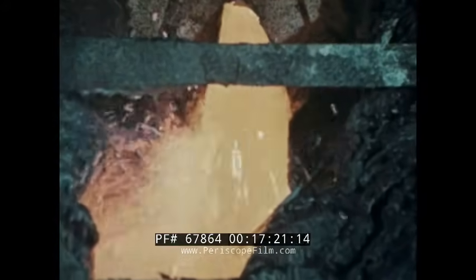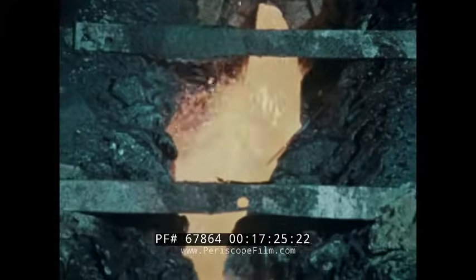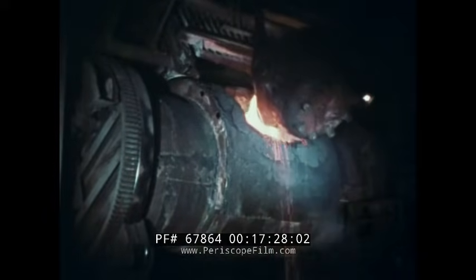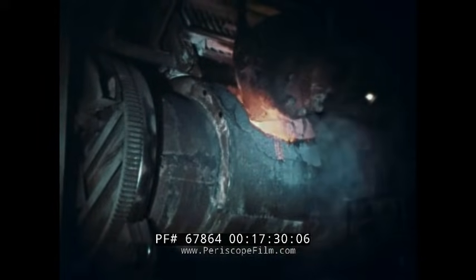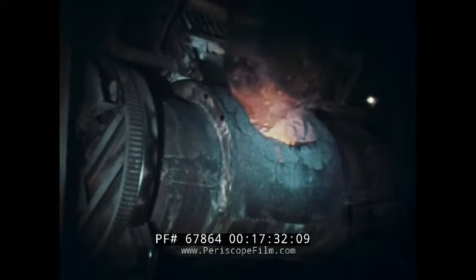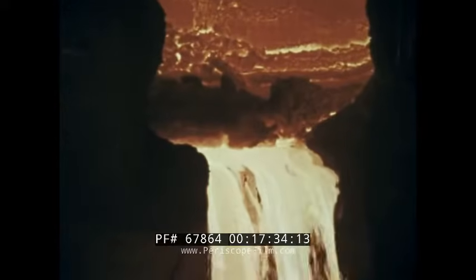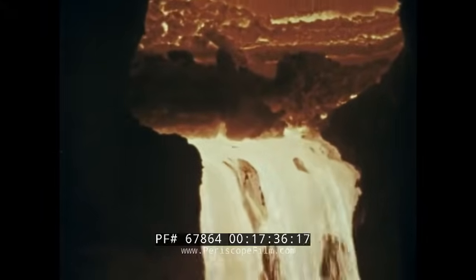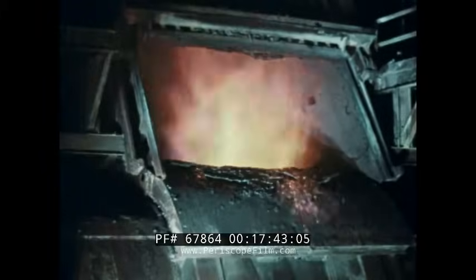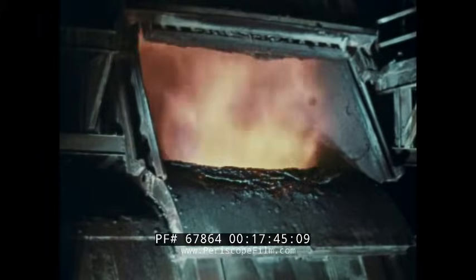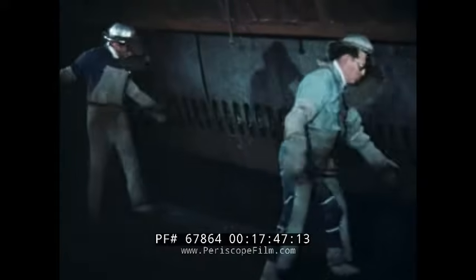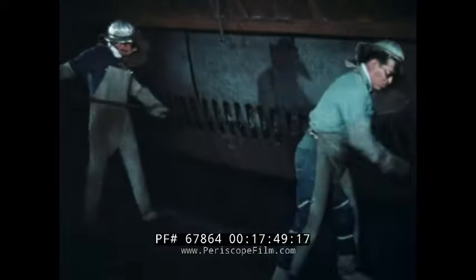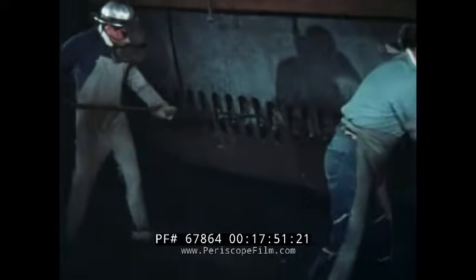The copper-bearing mat, which has settled to the bottom of the reverberatory furnace, is withdrawn and transferred to converters. In the converter, the remaining iron reacts with silica rock to form converter slag. Since this slag still contains some copper, it is skimmed and returned to the reverberatory furnace. Air is introduced to the converter to oxidize and burn off the sulfur. Frequent punching keeps the air ducts open.